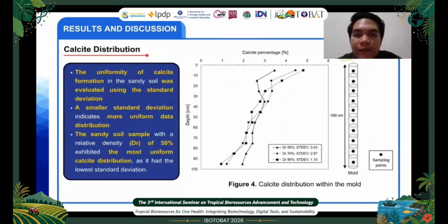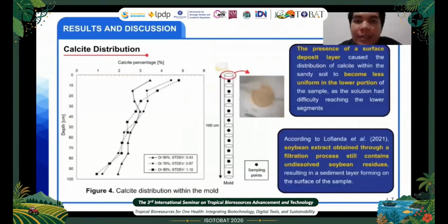The sand sample with a relative density of 50% exhibits the most uniform calcite distribution, owing to its low standard deviation value. The distribution of calcite in the sand sample was strongly influenced by relative density. In the sample with a relative density of 50%, the wider pore space allowed the SUCP solution to flow easily, resulting in more uniform calcite formation throughout the sample depth.